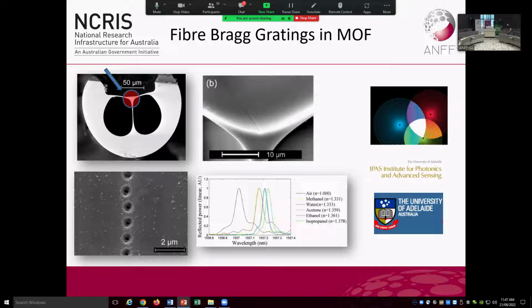This is a microstructured optical fibre from University of Adelaide, and what we've done, we've put a little Bragg grating, which is a periodic modulation on the fibre core, and we've done it with a femtosecond laser, and we've got features down here which are about 800 nanometres in size. The reason why I keep this example in, it just gives you an idea of the sort of process resolution you can start to think about, okay? We can put little dots and features on things which are about 800 nanometres in size. That's the lowest you sensibly go with these setups.